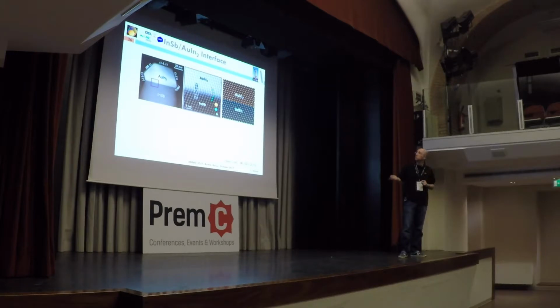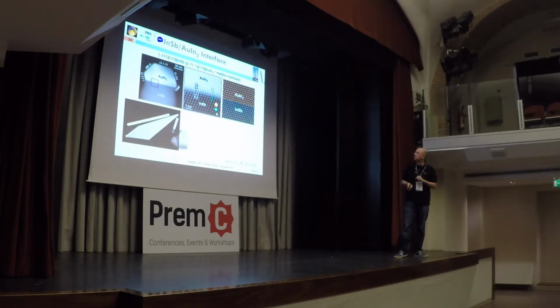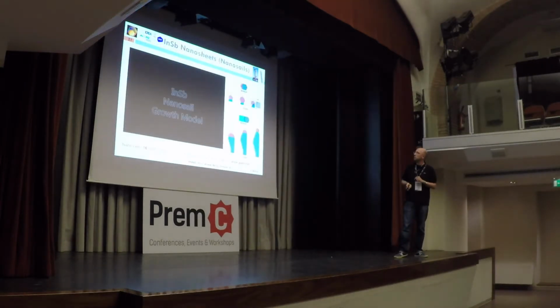And it's important to take into account also the catalyst seed. This is a catalyst seed after the growth. It's perfectly crystalline and epitaxial, but during the growth, this catalyst seed is liquid. So the problem is that in some of the structures, this liquid droplet will be the cause of the creation of this misfit dislocation, of this twin boundary dislocation. And I will show you how.